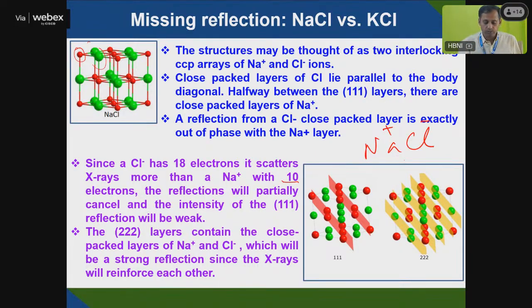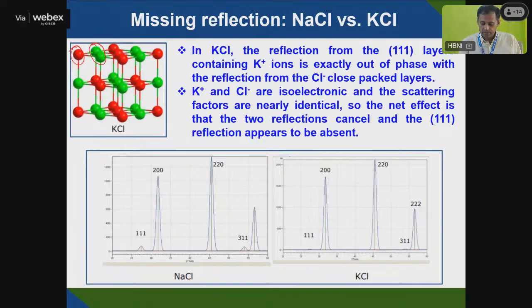So there will be a difference between Na plus and Cl, though they are parallel, interlocking with each other, so you will get a net result. So you will be able to see that 111 peak in NaCl. But in KCl, they are both isoelectronic. We will discuss the structure factor later. That means how much the X-ray will be scattered from Na and Cl, or K and Cl. In K and Cl, the scattering will be the same, so they will cancel each other. That 111 peak you will not be able to see in KCl, which you observed in NaCl.